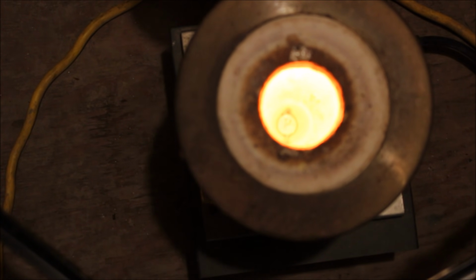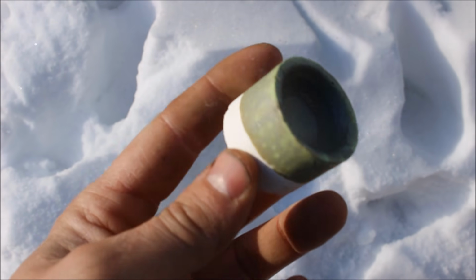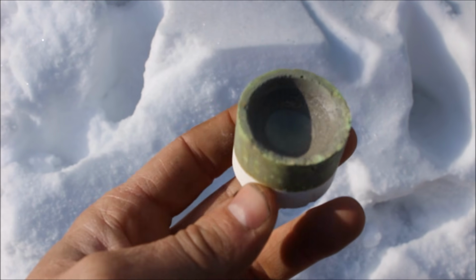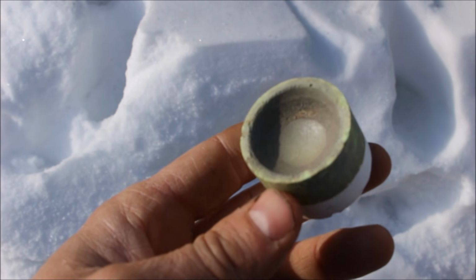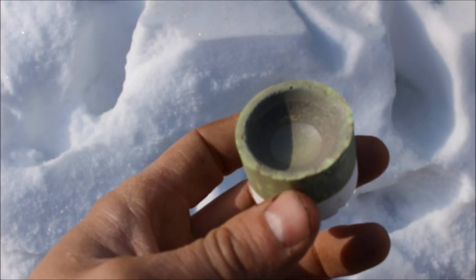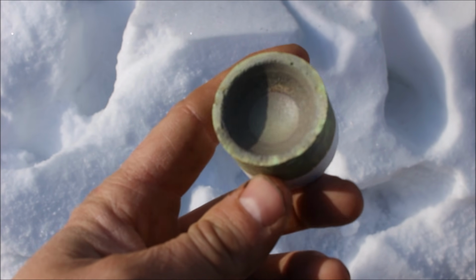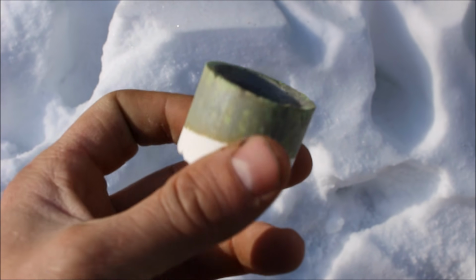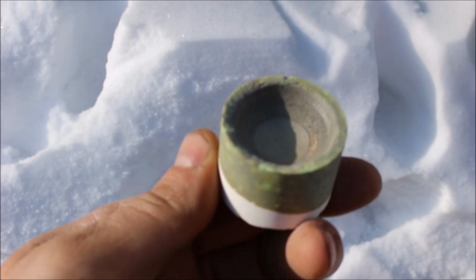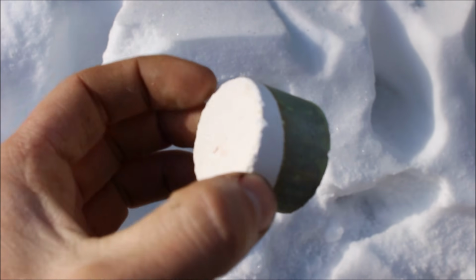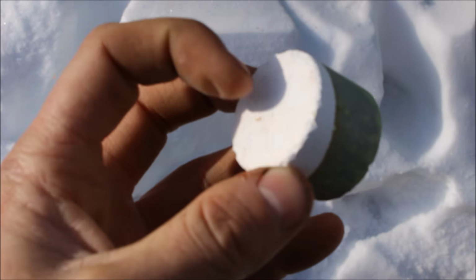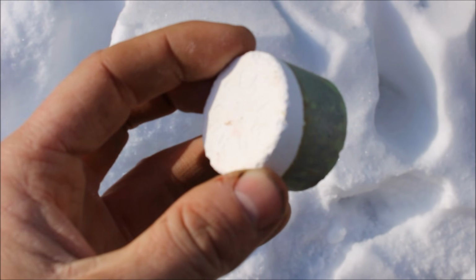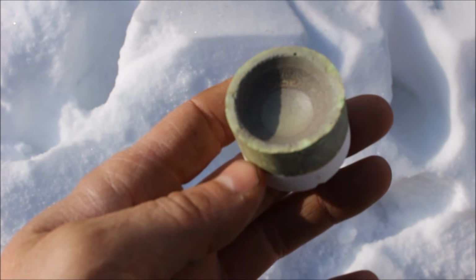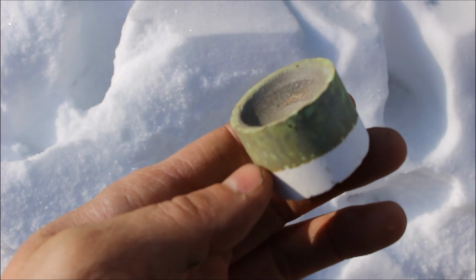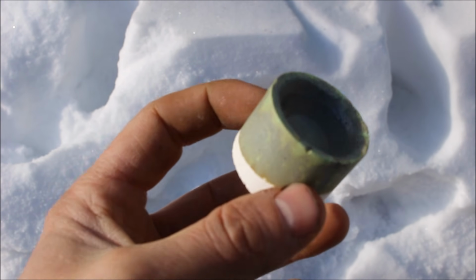There it is. I don't know if you can really see it because it's so bright. The cupel basically acts like a sponge. And just like a sponge, it won't absorb liquid metal. You know, if you've ever tried to soak up mercury with a sponge, you just can't do it. However, lead oxide will absorb into a sponge. And that's exactly what's happened here. The calcium phosphate of the cupel is very porous, and the lead oxide can flow into it and be absorbed.